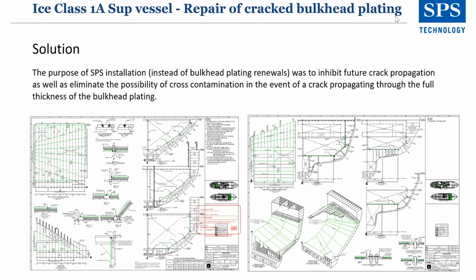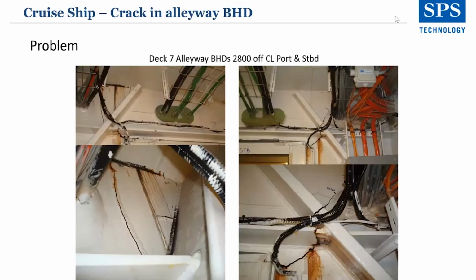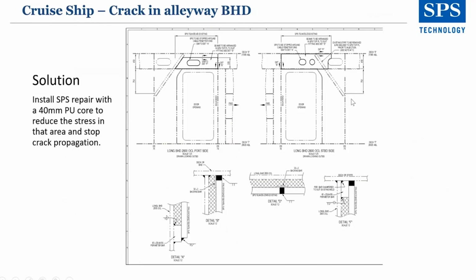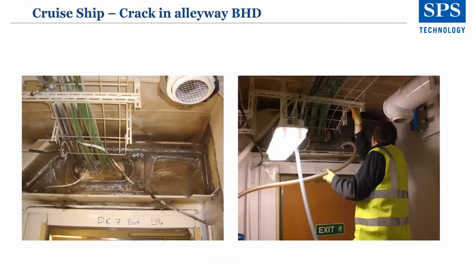The purpose of the SPS installation was to inhibit future crack propagation, as well as eliminate the possibility of cross-contamination in the event of a crack propagating through the full thickness of the bulkhead plating. And I've been shown the drawings there for reference. On the cruise ship, we had a crack in the alleyway on deck 7. The photographs, as you can see here, this is a close-up view, and this is above the doorway itself. So the crack had propagated on both sides, and an SPS was installed to reduce the stress in that area and stop further crack propagation. So we didn't want the crack coming back after the repair was installed. A 40mm PU core of SPS was installed for this application.